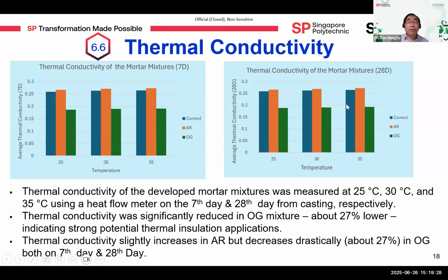The thermal conductivity of the developed mortar mixtures was measured at 25, 30, and 35 degrees Celsius using a heat flow meter on the 7th day and 28th day from casting respectively. The thermal conductivity was significantly reduced in the OG mixture, about 27% lower, indicating stronger potential for thermal insulation applications. Thermal conductivity slightly increased in AR, but decreased drastically, about 27%, in OG, both at 7 days and 28 days. These two bar charts show the average thermal conductivity of the mortar mixtures at 7 days and 28 days respectively.